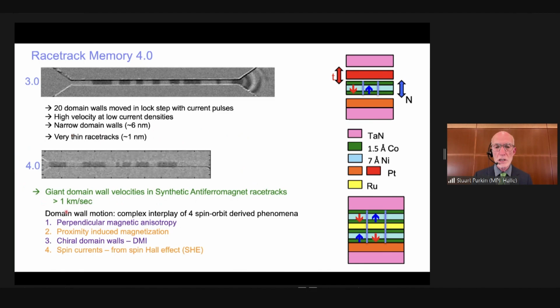And in the lower figure, you can see images of domain walls moving in a synthetic anti-ferromagnetic racetrack at speeds of more than 1 kilometer per second by introducing current pulses. So the physics is a rather complex interplay of four spin-orbit-derived phenomena that I won't have time to discuss, but most importantly, these domain walls actually have a chiral spin structure.